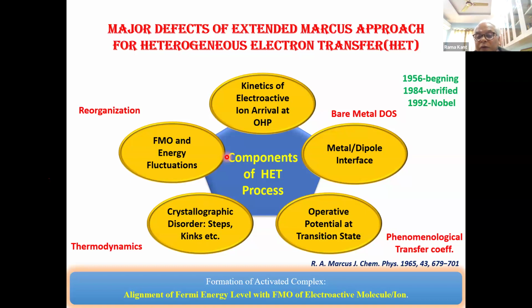And then they have the metal dipole interface. In the modified version of even Marcus theory, they use the bare metal density of states, but when we put solvent over the metal, it changes the whole distribution of this density of states. So that averaging will not solve the problem. Then there are frontier molecular orbital and energy fluctuations due to solvent. It is accounted for in Marcus theory through reorganization energy, but the problem is that the electrode is a large system, so it does not follow exactly what you do for the electroactive species. Then there are kinds of crystallographic disorder, etc., kinks and steps, those are difficult to account for because the electrode is missing more explicitly in that theory.